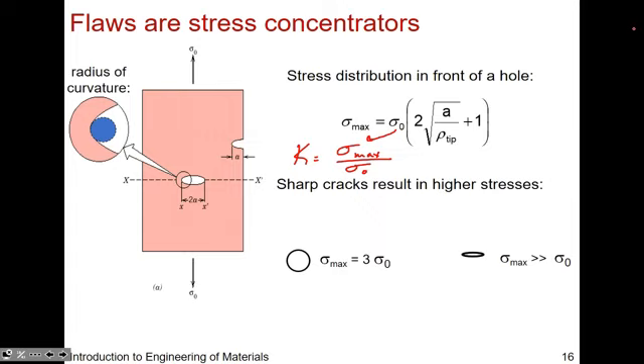So if you're applying a load, even though you say, well, it's still below that yield strength, it's still going to be concentrated, and the relationship is this equation right here. Okay, and so this rho at the tip is just your radius of curvature. So if you have a circle, your radius of curvature is just the radius of your crack. a equals rho. Okay, so it's a divided by rho, which is just 1.